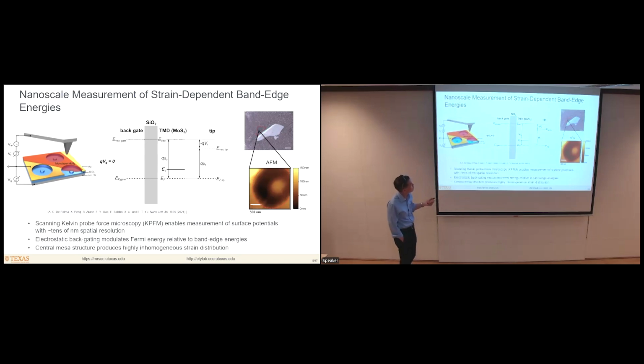All right. Now, what happens in the Kelvin probe microscopy measurement is that you have a probe tip and a sample, and they have different work functions. Okay, so when you bring them into close proximity, there's a potential difference between them. And what happens then is that a bias voltage is applied to the tip to zero out that potential difference. And that gives you a way to measure local variations in the surface potential, the work function of this material. Okay, so that's the standard Kelvin probe microscopy technique.